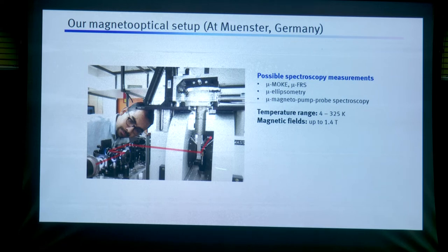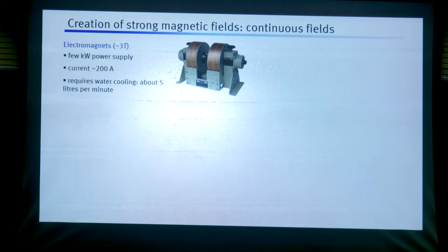So there are many things possible, Faraday and Kerr effect spectroscopy on micron scales. That's why I write micro. So you can specially probe micron dimensions, which is required for studying two-dimensional materials. Temperature ranges from 4 to 325 Kelvin, and this is a small field up to 1.4 Tesla, not a very large field.